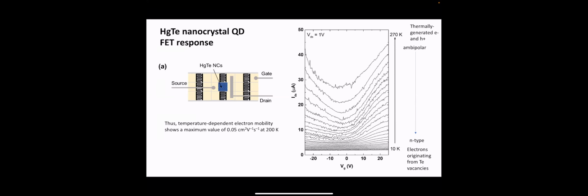The electron mobilities aren't particularly high, at least for the materials we make. I mean, you're talking like 0.1 centimeter squared per volt second, probably at room temperature. So you can make photodetectors out of these. The mercury telluride nanocrystals, at least spherical nanocrystals, most of them that we make just with oleylamine, if you drop them onto a device structure, there's really no photoconductive response.